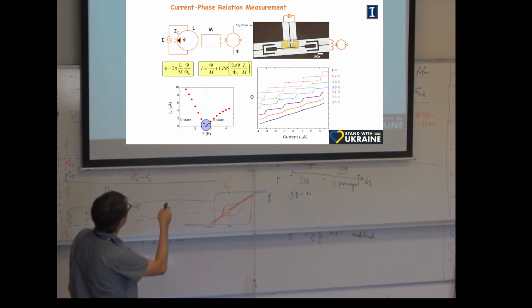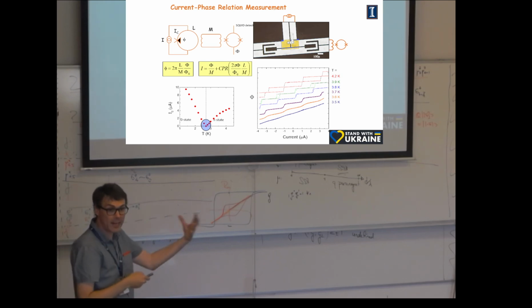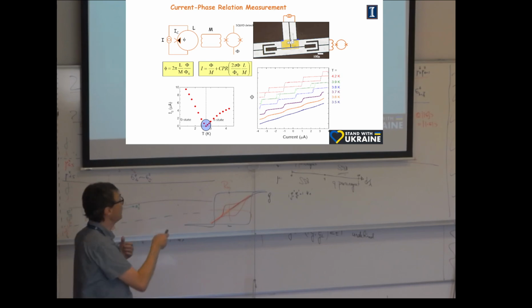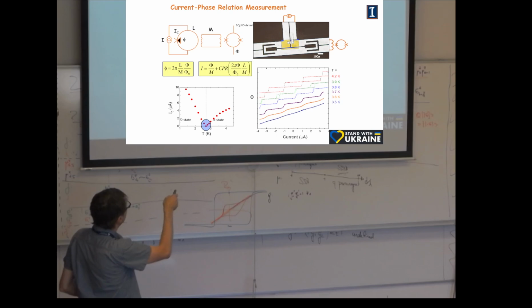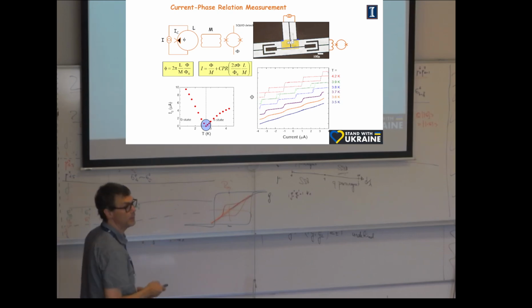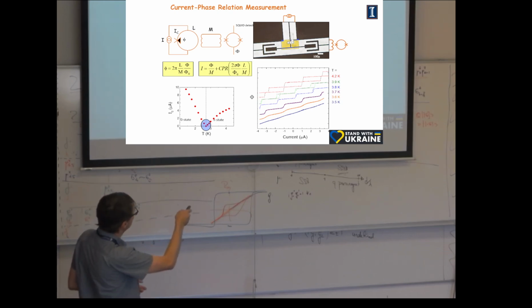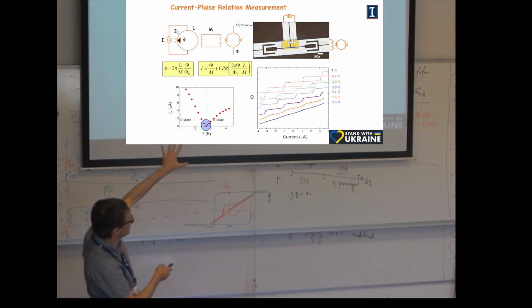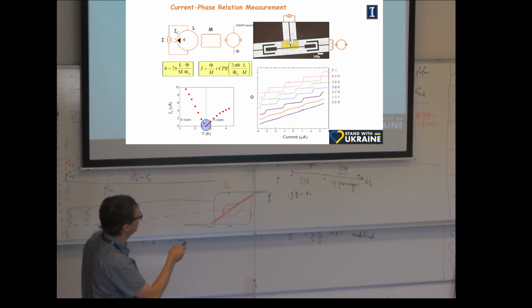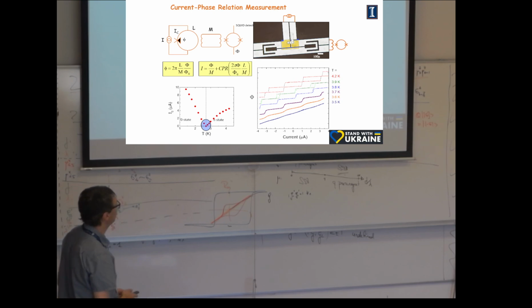And we put one junction in a loop and measured directly the current phase relationship, right? You pass the current and you measure flux through some inductive coupling with this SQUID. So this is the sample loop, this is the loop. Pass the current here, there's a ferromagnet here. This is a tri-layer junction viewed from the top, 100 micron scale. This goes to the flux detector through this inductor. It generates current in this loop and it's picked up by a flux detector. And you get these kinds of curves.